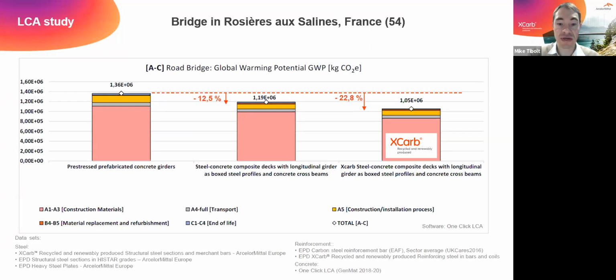But you can see, first, that the salmon color is dominant, and this is the global warming potential coming from the construction materials, the stages A1 to A3, which is dominant here for this bridge. And you can see that by switching from concrete to the steel-concrete composite deck, we could already save 12.5% of CO2 equivalent. And if it had been possible to use XCarb, we can see that compared to the concrete solution, we can save an additional 22.8% of CO2 equivalent.